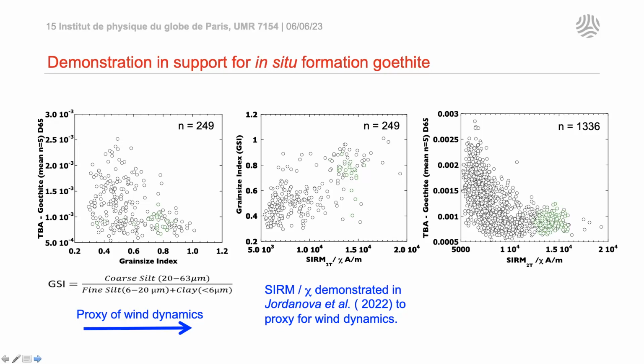So the grain size index is the ratio of coarse silt to the combination of fine silt plus clays. As this grain size index increases, wind dynamics increase, more material is being brought in. So for the whole section, there's only 249 granulometry data that were acquired so far. But you can see from those already that there doesn't seem to be much of a correlation. The green dots are the samples within the glacial 12 unit that we're looking at more closely at the moment.